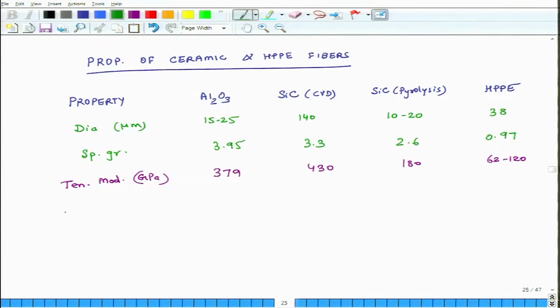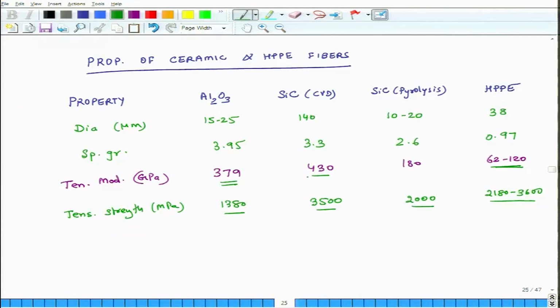And then let us look at strength. This is in MPa, so 1380, 3500, 2000 and this is 2180 to 3600. So, this is the main thing. If you divide these numbers by their respective densities, you see that the specific strength of HPPE is really very high. Even its specific tensile modulus is also pretty high compared to that of alumina and silicon carbide fibers, because once you divide 120 by 0.97, you may get something like 130, but if you divide 379 by 4, you will get less than 100.